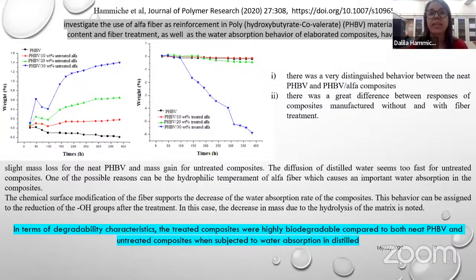In this case, the decrease in mass due to the hydrolysis of the matrix is noted, and the fibers acted as a base for the water diffusion in the biocomposite. In terms of degradability, the treated composites were highly biodegradable compared to both neat PHBV and untreated composite when subjected to water absorption in distilled water. Here, I mean that after treatment, we can accelerate the degradation of these composites.